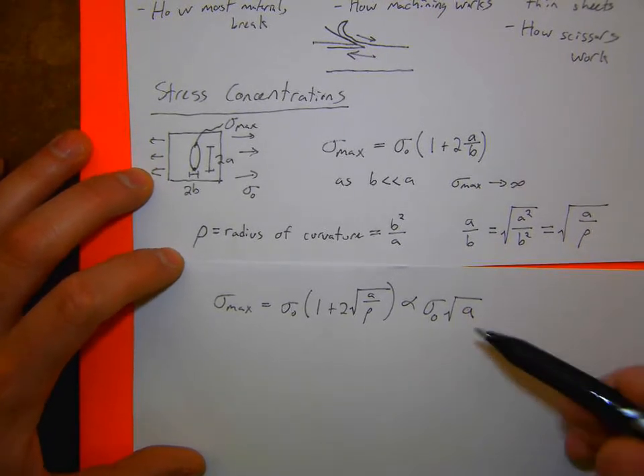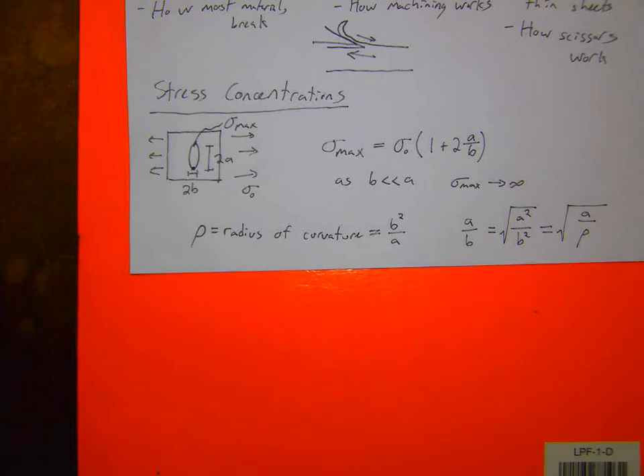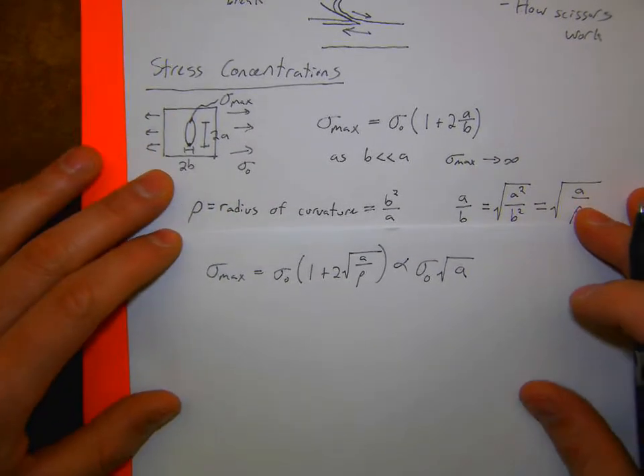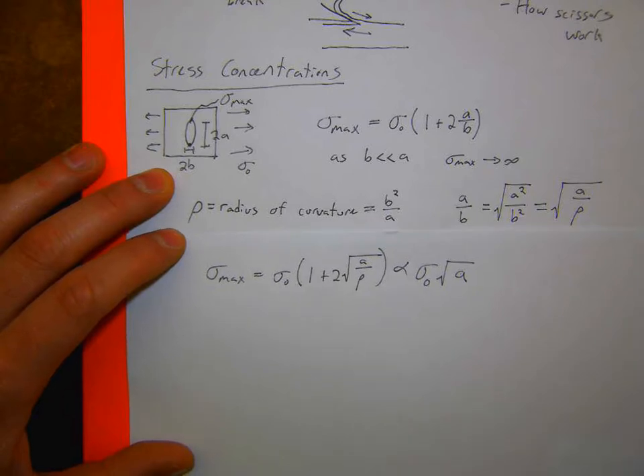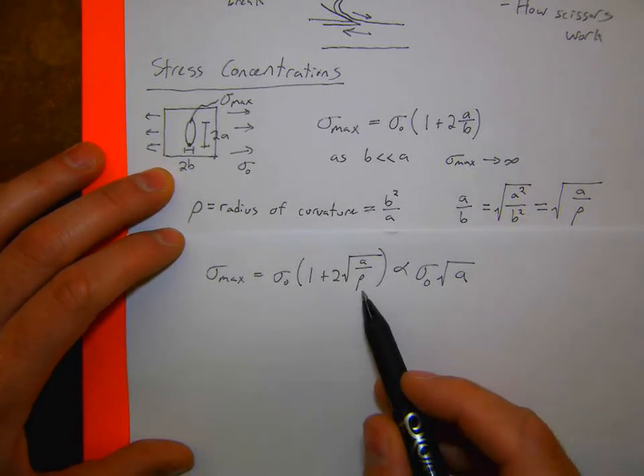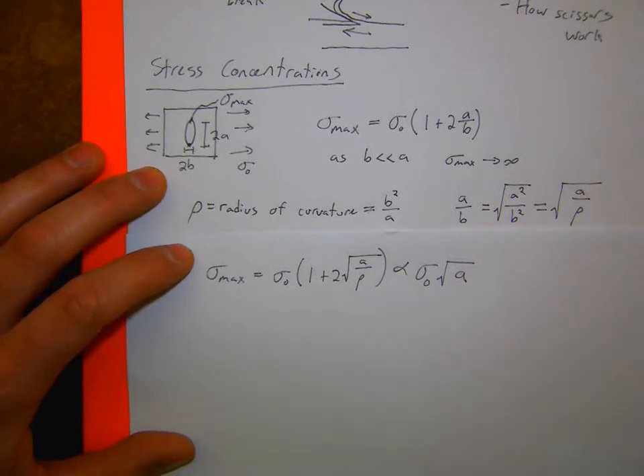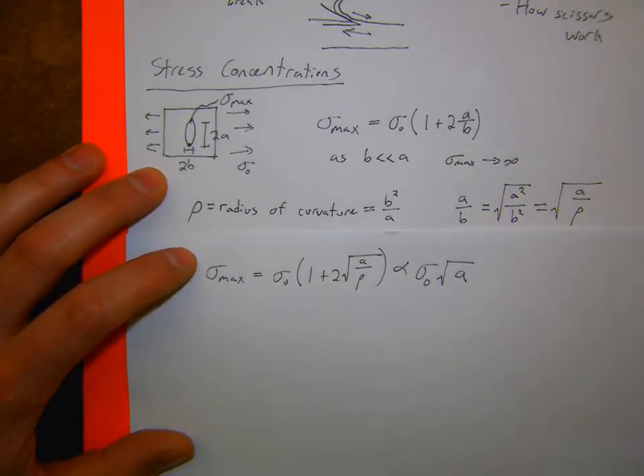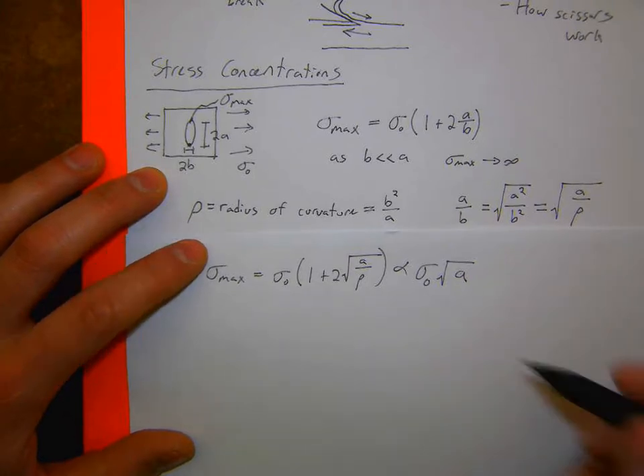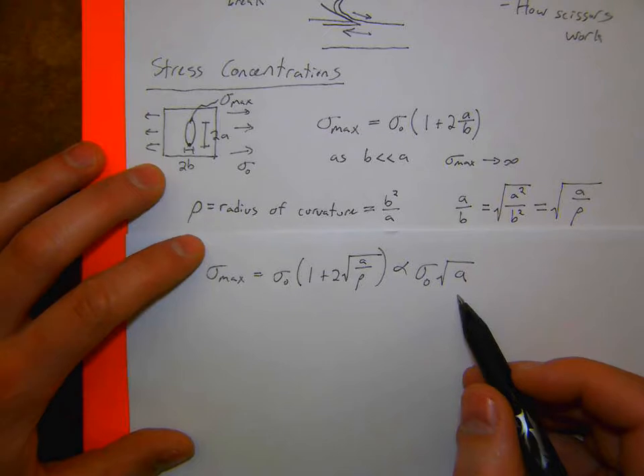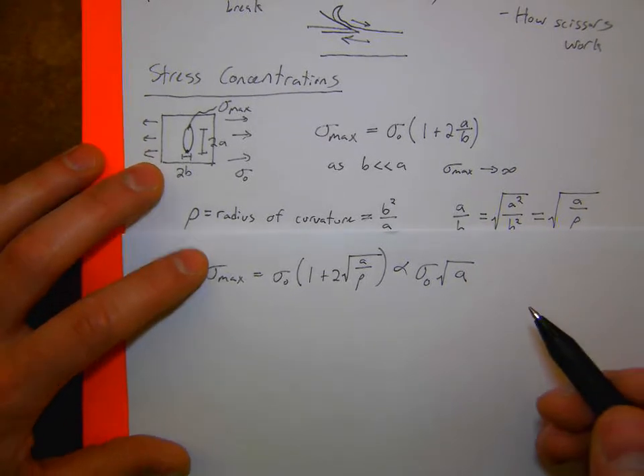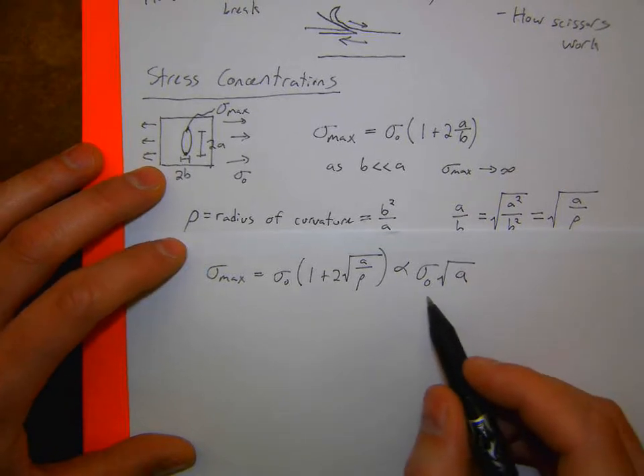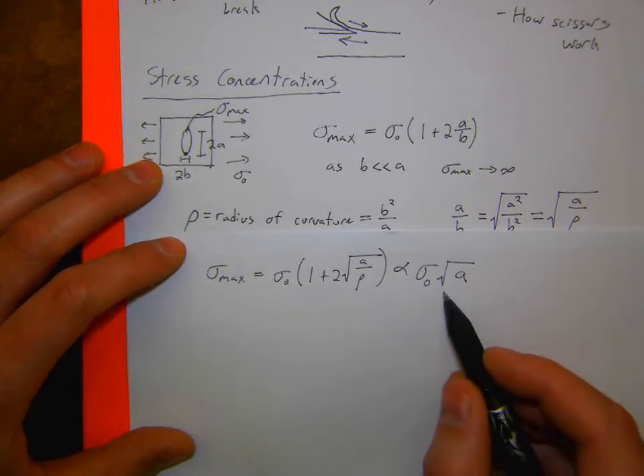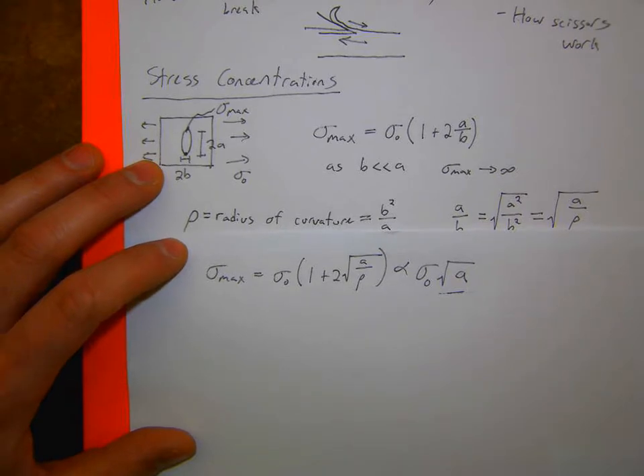For all of our fracture analyses, you have to be able to make a measurement for your parts, and this radius of curvature can change very significantly depending on exactly how the crack formed, whether it was intentionally included, or whether it was a nucleation event. But it's easier to measure the length of the crack, especially for something that's a high aspect ratio. So most of our fracture analysis will be based on this square root of a, because physically that's the easiest thing to measure. So let's get into some of the history of fracture.